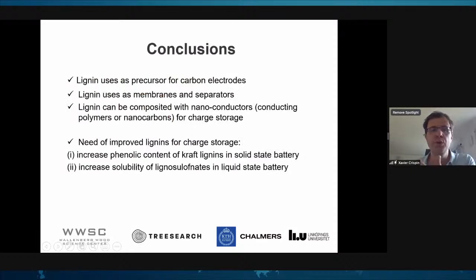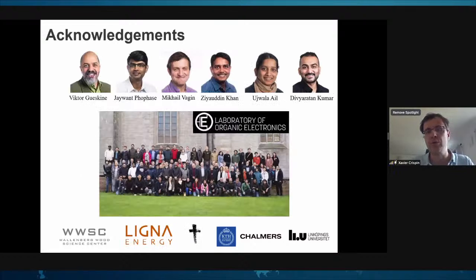So in conclusion, lignin can be used as a precursor for carbon electrodes, as a membrane separator, and if you want to composite it with a nanoconductor, such as a conducting polymer or nanocarbon, you can obtain a nanocomposite for charge storage that is very cheap. What needs to be improved in lignin is increasing the phenolic content, as well as increasing the solubility for the liquid-state batteries, basically. So I thank a lot of co-workers, the Laboratory of Organic Electronics, and I thank you for your attention.